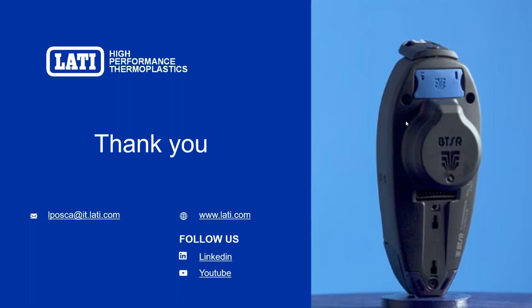The first question is: have you got already available grades featuring carbon and stainless steel? Yes, we have. I told also along the way that this 50% steel with carbon fiber was one of the first products that we developed. Now we have at least another 4 or 5 different grades. We are working with PPS, with nylon, with aromatic polyamide, changing the ratio between carbon and steel in order to find the best mixture, because it is not straightforward to injection mold steel fibers. So it would be a great success if we could find that maybe 5 to 7% steel is already capable with 15 or 20% carbon to provide a very all-around effective solution. Anyhow, get in touch with our salespeople or with technicians, and we will be happy to answer your questions.